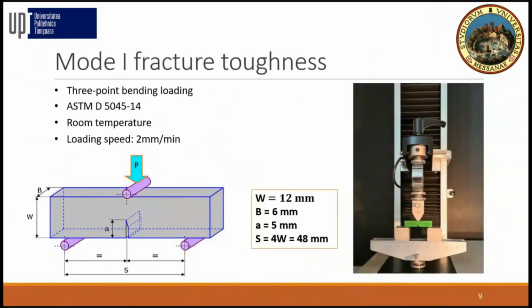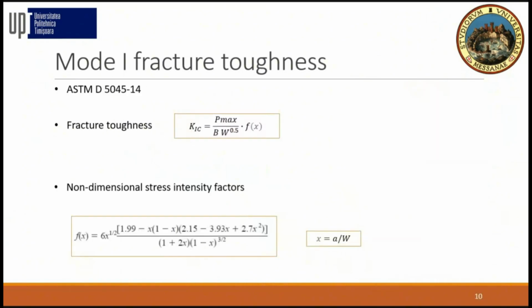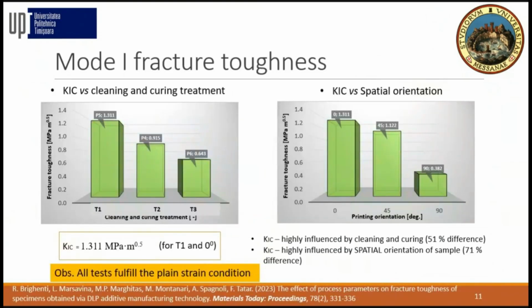For the results, we follow the ASTM D5045 standard. We use single edge notch bend specimens loaded in 3-point bending. We did the test at room temperature with 2 millimeters per minute. These are the dimensions of the specimens. We use the classical, standard relations for determining the fracture toughness. These are some results.